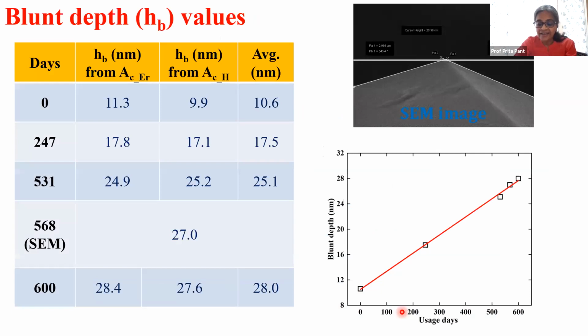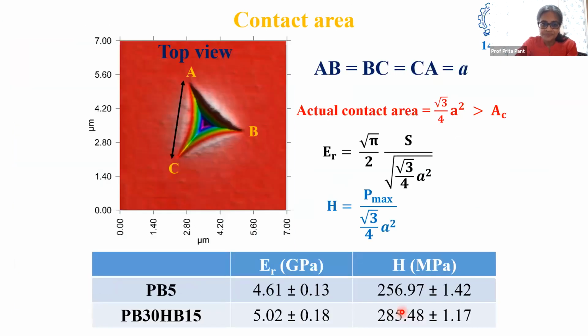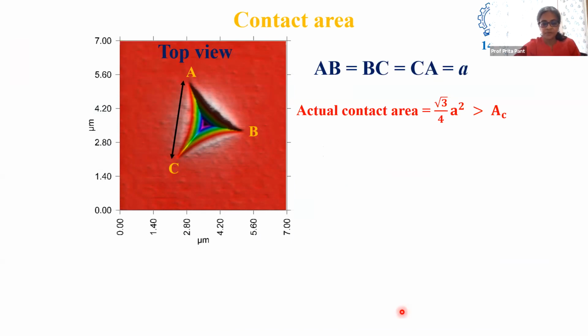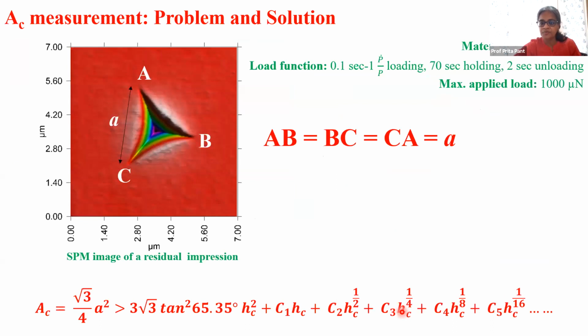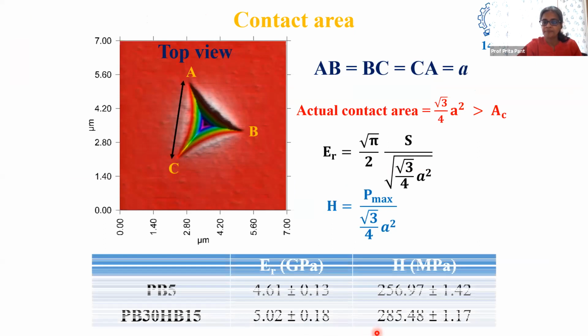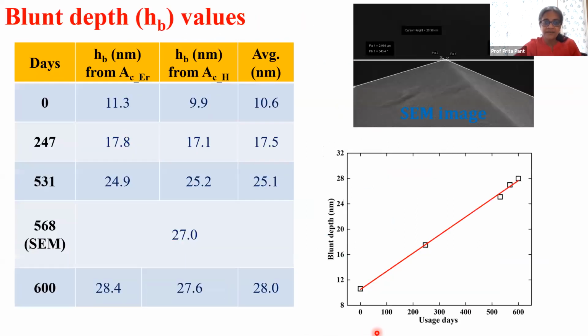Okay. And why was this happening? The reason this was happening is, of course, because of this correction that we end up using, right? This correction was not working quite well for our system. So we did an estimation of the blunt depth. Now, to explain to you what a blunt depth is, you remember I said a perfect tip, right, or rather we assume that it's a perfect tip.